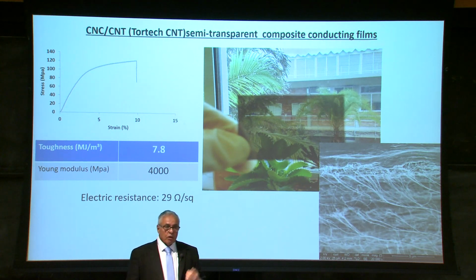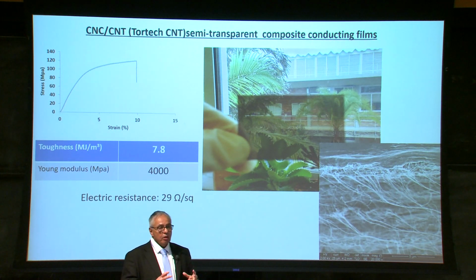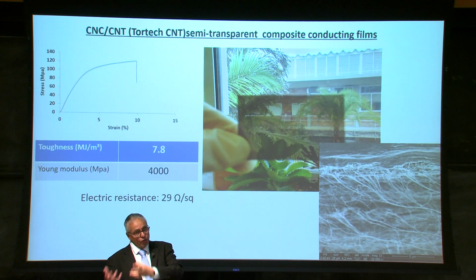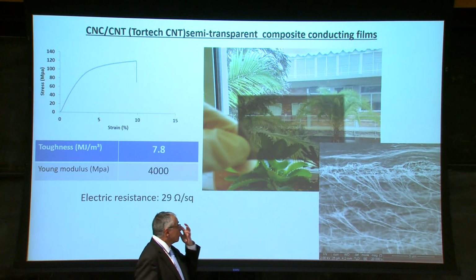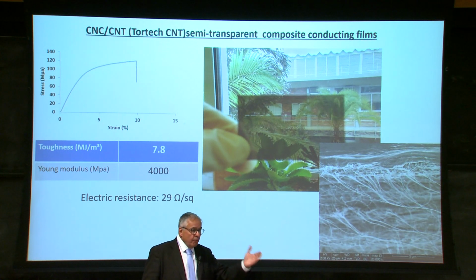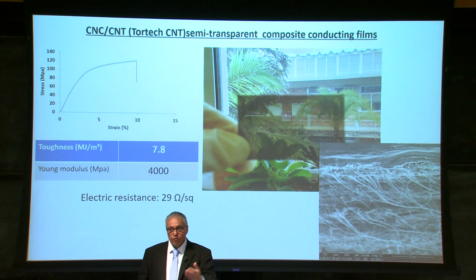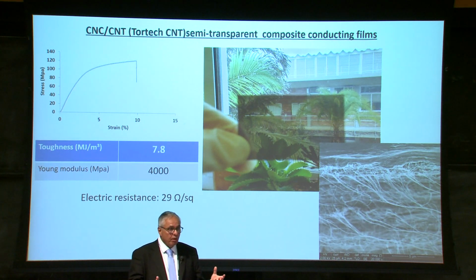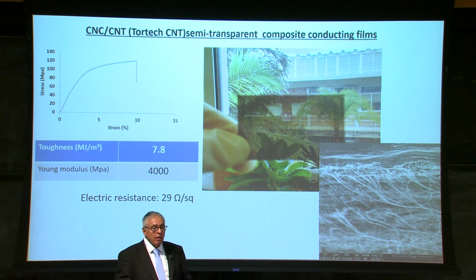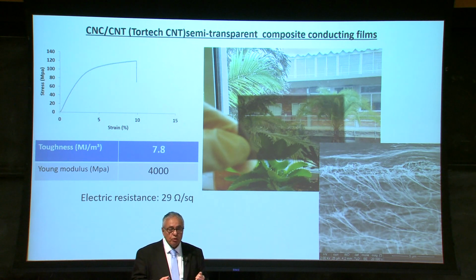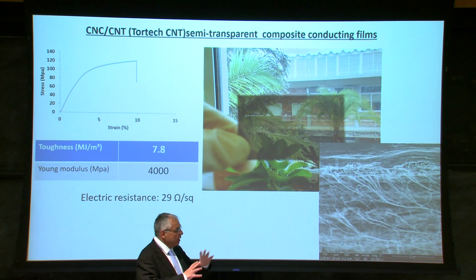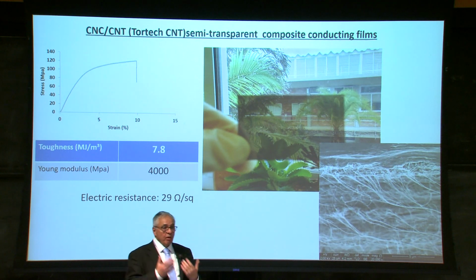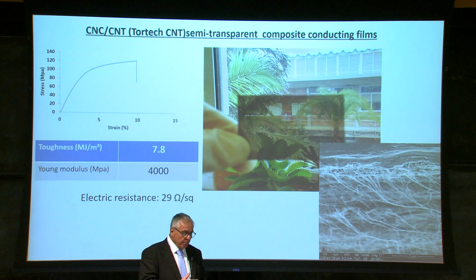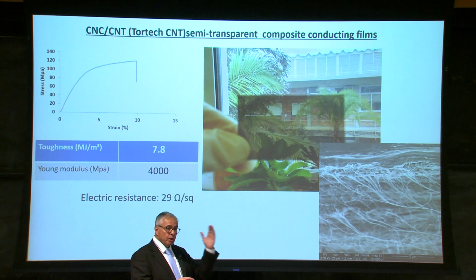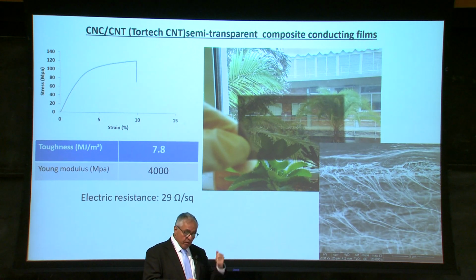Another interesting feature of cellulose nanocrystals is the fact that they are actually amphiphilic. They have both hydrophobic sites, but also hydrophilic sites. So taking even material like carbon nanotubes, they are very difficult to suspend in water. You can add cellulose nanocrystals, either raise some temperature or a little bit of sonication, and you get really nice dispersion. And when you then cast it as a film and evaporate the water, as you can see, you can get even semi-transparent films that are very, very strong.